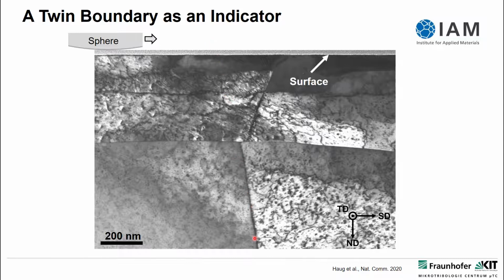What we know here is that we have a grain boundary, but it's not just an ordinary grain boundary, it's a specific type: a twin boundary. So this is the first thing we notice. We have a twin boundary here, an annealing twin, which happened in the material during heat treatment, in the copper. It's high purity copper again here.